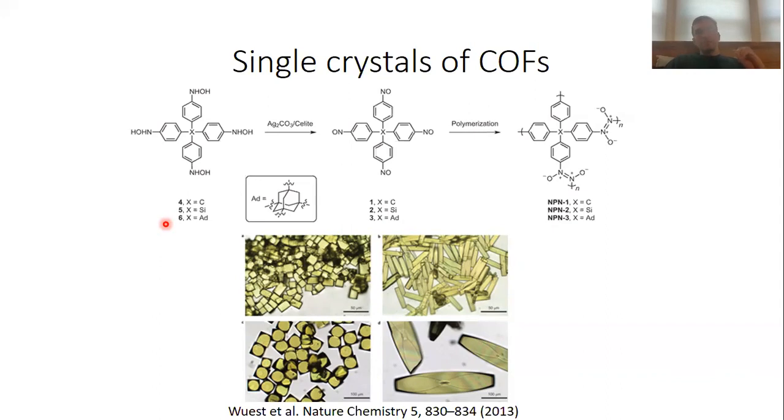So to some extent, the directed nature of the covalent bond helps us because it actually allows us to predict structures, to just draw the most simple structures on a sheet of paper, then simulate the X-ray diffraction pattern, and then just see if that simulated X-ray diffraction pattern is in accordance with the experimental X-ray diffraction pattern that we measure.